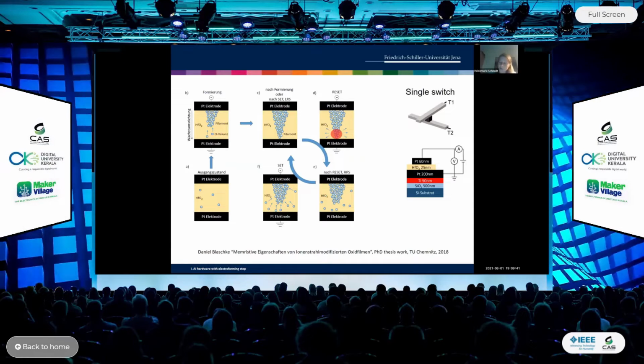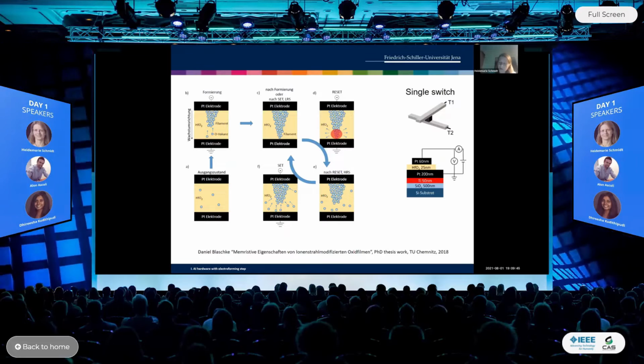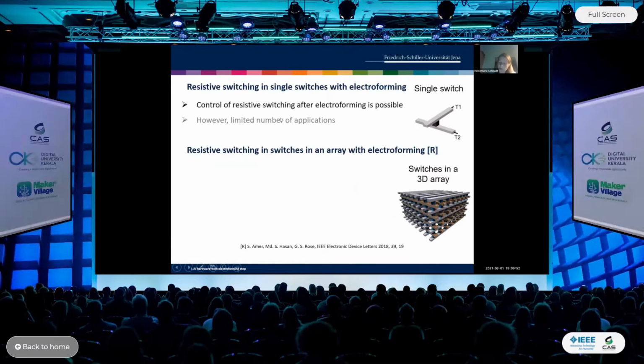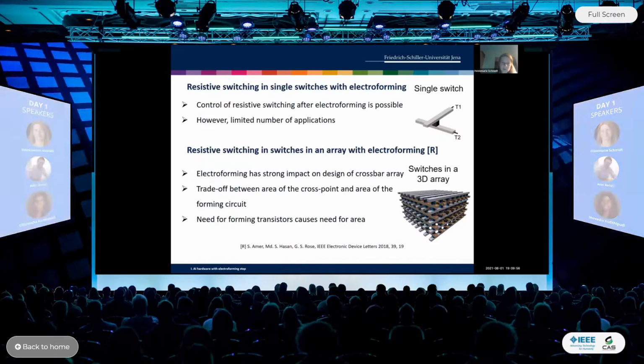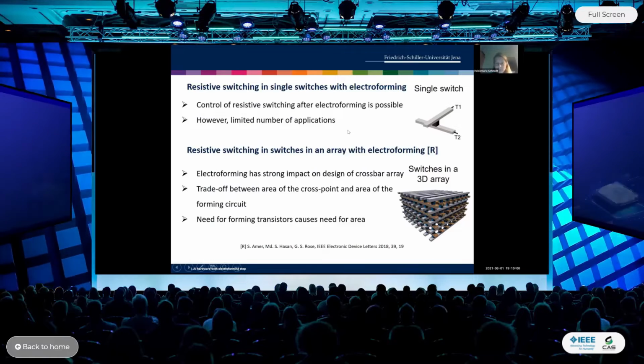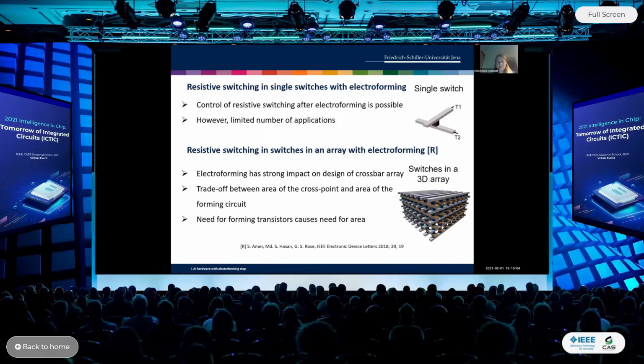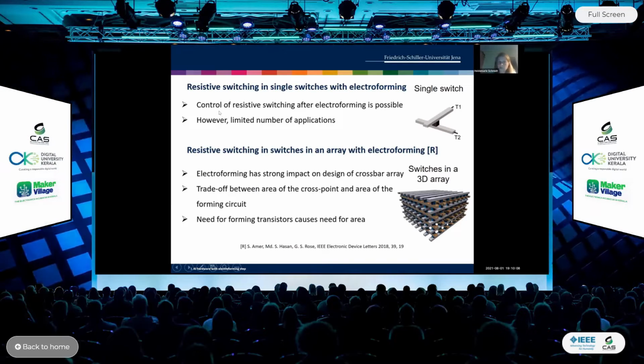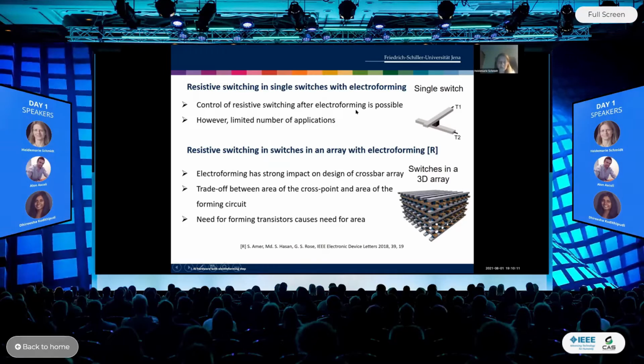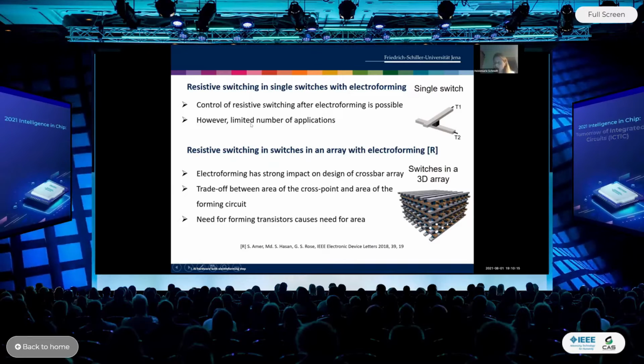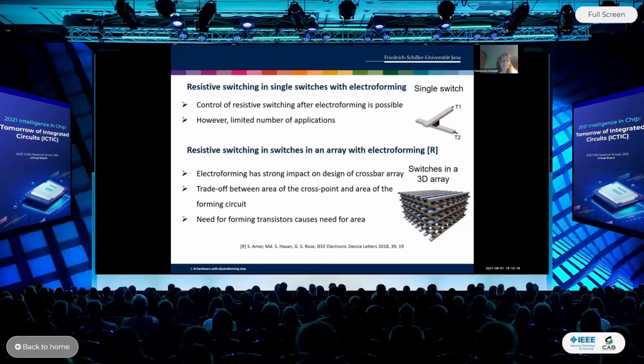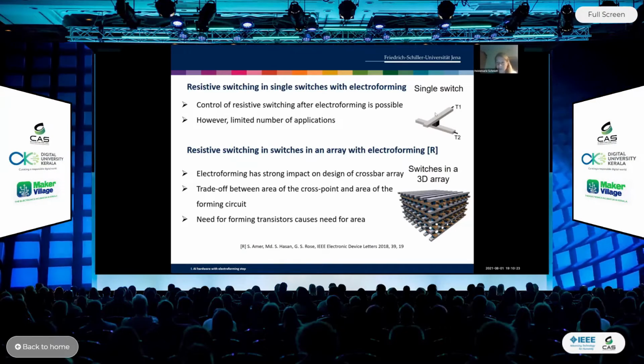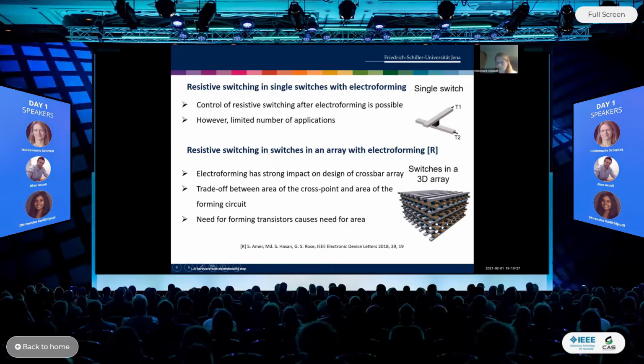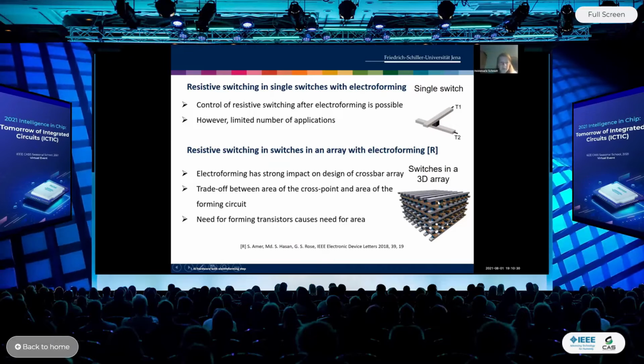And actually, if one needs a material which does not need this electroforming step, then you have to look for one. And just to summarize why it's really important to look for such materials, I would like to summarize the properties of memristors where electroforming is needed. One can also control the resistive switching after the electroforming, if this electroforming is possible. However, the number of applications for such memristors which need an electroforming step is rather limited. And this is related with the fact that they cannot easily be integrated without any selection transistors in 2D or 3D arrays of memristors.